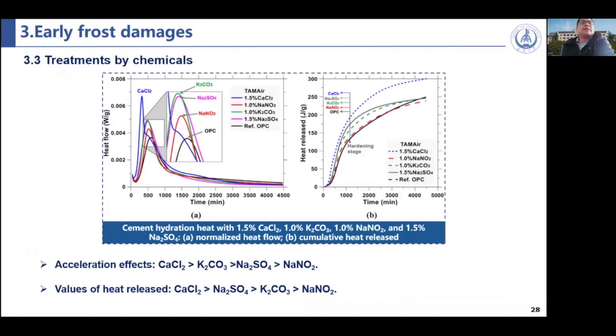We also measured the heat flow and the heat release during the cement hydration. We can see the peak and the values of the heat release are different and changed by the chemicals used in the cement mixtures. What I want to show is you can see here the calcium chloride has the fastest cement hydration and is the first one to achieve the peak.